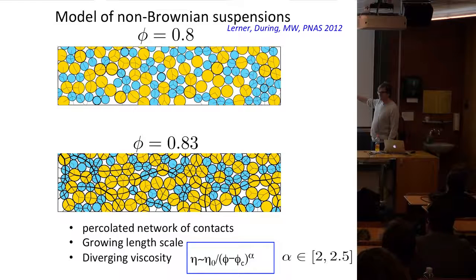But it turned out that with this simple model, you could do a more realistic model where you would have drag, since it's believed that what dominates dissipation are lubrication forces between particles. So if you put a drag that has to do with relative motion of particles, you get the same scalings as far as the jamming transition is concerned. Numerically, that seems to be the case, and theoretically, we think it should be the case too. Okay, but let me show you the movie.